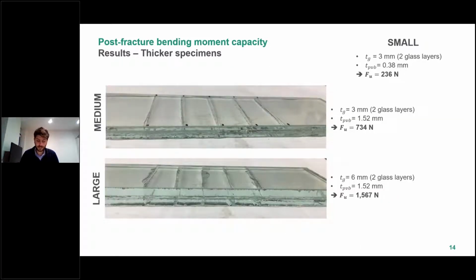The exact same tests were also repeated on specimens with both thicker glass layers and thicker interlayers. An increased ultimate loading capacity and therefore post-fracture bending moment capacity was recorded consistently for all the thicker specimens tested. Therefore, the experimental results were in agreement with the predictions of simple bending theory.